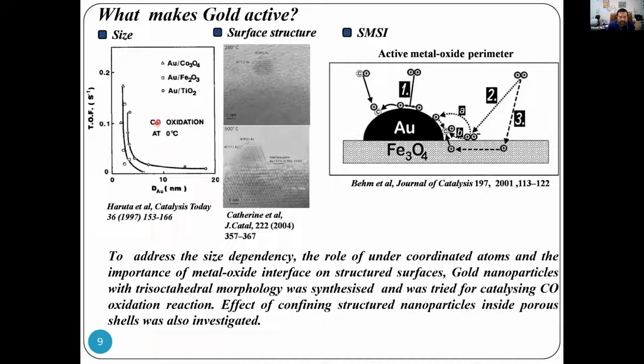For example, if you're looking at a reaction like carbon monoxide oxidation, gold supported on reducible oxides like cobalt oxide, iron oxide or titanium oxide become excellent catalysts. The activity can also be because of the strong metal support interaction that gold has with some of these oxides, where the mechanism of carbon monoxide oxidation has been nicely elucidated by Jürgen Behm from Ulm University in this paper in the Journal of Catalysis.